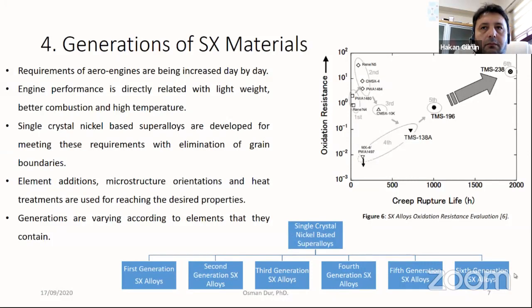Requirements of aero engines are increasing day by day. For example, some aero engines should be available for supercruise mission conditions, which need higher temperature creep resistant materials. Engine performance is directly related with light weight, better combustion, and high temperature. Single crystal nickel-based superalloys were developed for meeting these challenging requirements with elimination of grain boundaries. Element addition, microstructure orientations, and heat treatments are used for reaching the desired properties. Lastly, the generations vary according to the elements they contain.